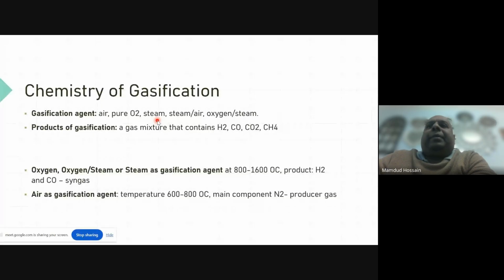When you have a gasification process, at the end what you get is hydrogen, carbon monoxide, carbon dioxide, and methane. If you use oxygen and steam, or steam, as a gasification agent, we can get hydrogen and carbon monoxide as a syngas type product, at a temperature of 800 to 1600 degrees Celsius. If you use air as a gasification agent, we can use a slightly lower temperature, that's fine, but the main component is nitrogen. So you have a massive amount of nitrogen that you need to heat up, but it doesn't do much in your process.